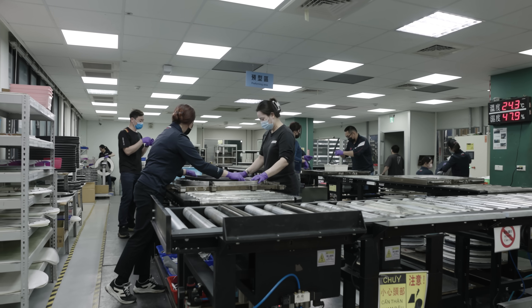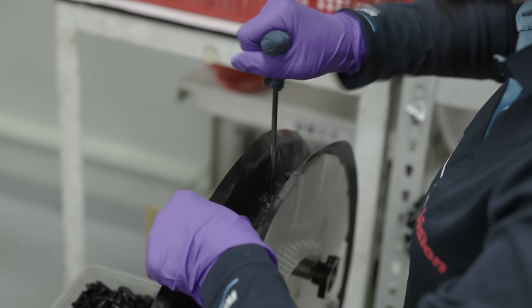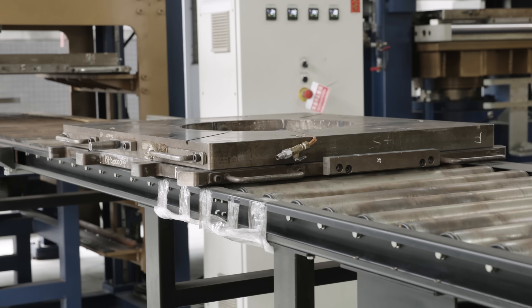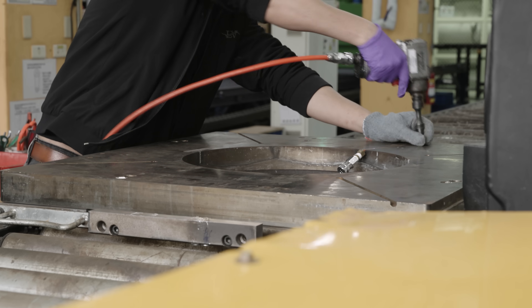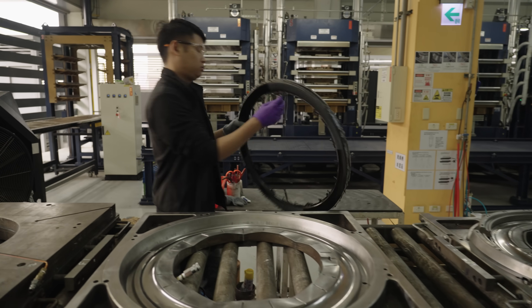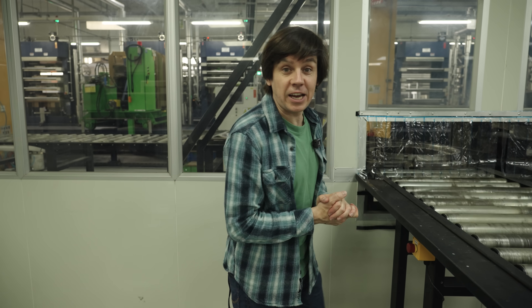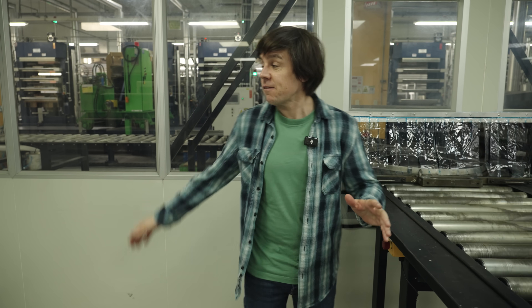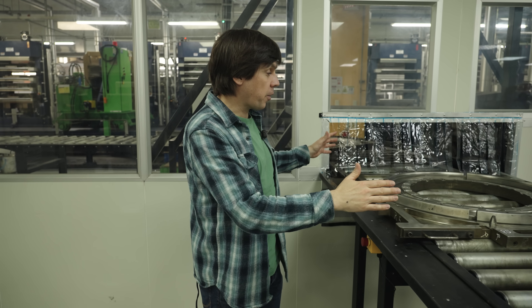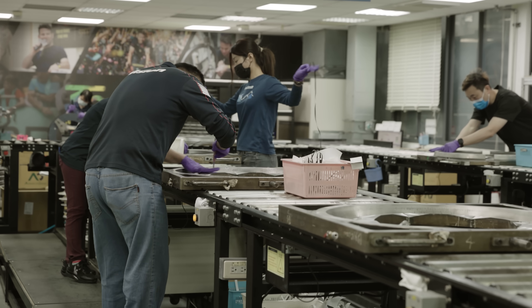The curing process is the heart of the carbon rim manufacturing process. The mold with the laid-up carbon fiber and internal air bladder are heated and cured. The heat activates the resin, and the internal bladder inflates, pressing the carbon layers tightly against the mold walls, ensuring proper compaction and removing air bubbles. Here's a conveyor belt coming from the curing and cooling process — one of the molds coming through, which will be cleaned up and ready to be laid up again.